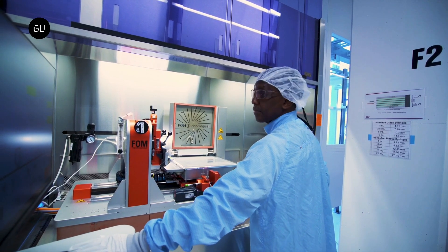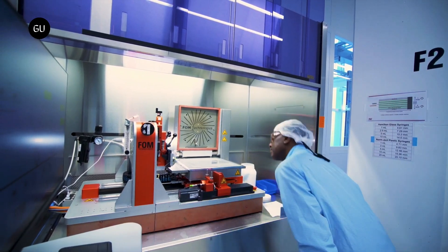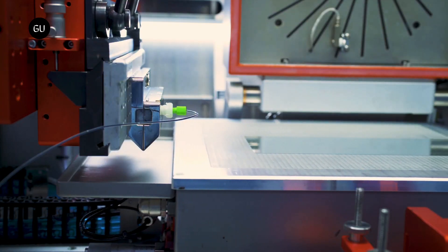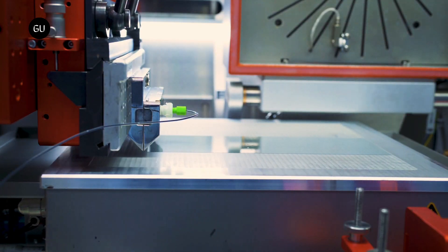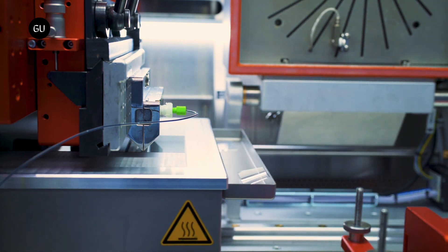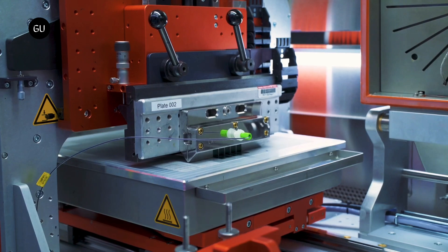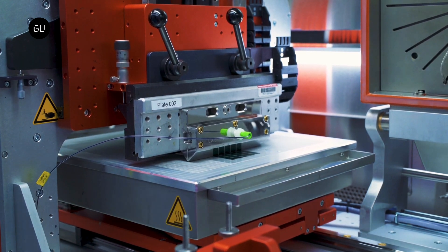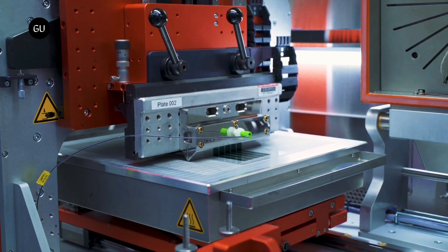This fabric is made of fibers that are so strong they were used as ropes to lift the sunken cruise ship Costa Concordia from the bottom of the Mediterranean Sea. By adding a layer of UV curable glue, which is only a few microns thick, they adhere the solar modules to sheets of this fabric. This forms an ultralight and mechanically robust solar structure.